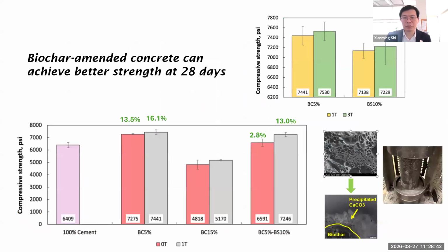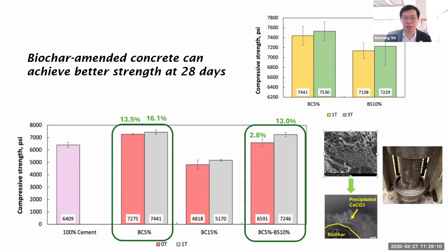We want to test them. First, the good news is that biochar amended concrete can achieve better strength at 28 days than the control. You can see here 100% cement concrete is around 6,400-ish PSI. And then you look at 5% replacement of cement using the fine biochar, then you're achieving some improvement of the compressive strength. Similarly, this one is 5% of cement being replaced by fine biochar and 10% of the sand being replaced by coarser biochar. And again, we're seeing benefits in some of the mix designs.